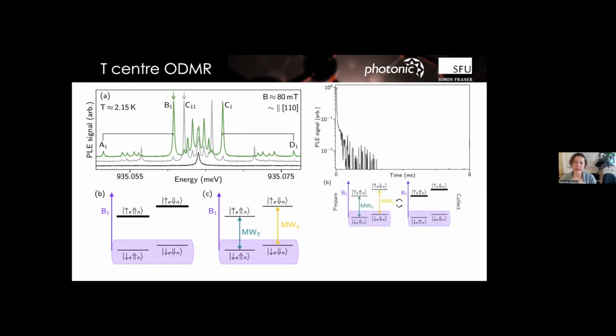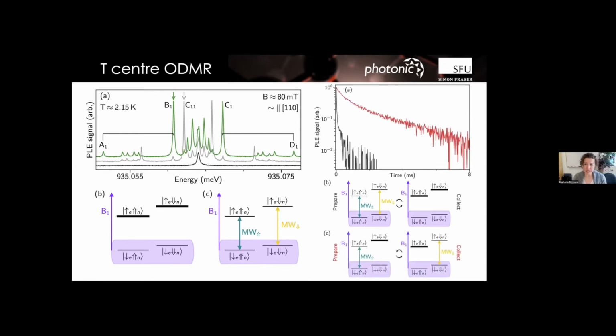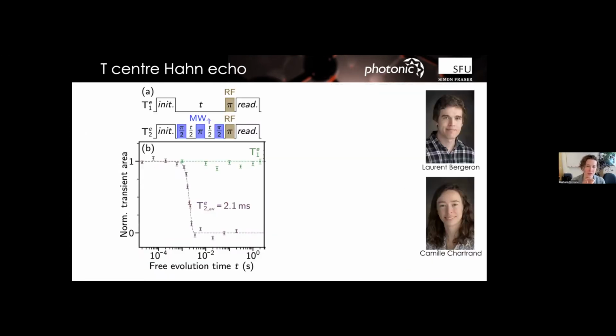And so that allows us to give a readout scheme, which I'll skip through a little bit, but basically you can get spin readout this way. You can actually drive a cycling transition through the nuclear spin, and the details are in the paper if you want to go look. But the real conclusion is that these things behave like good spin qubits. And again, this is what you'd expect. What we see over and over in silicon is, especially for unpaired electron spins, the noise seen by those spins is